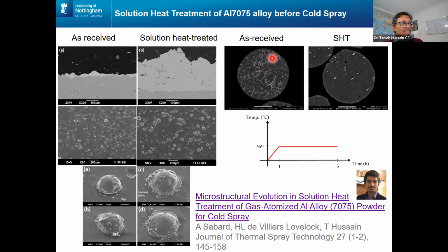And these alloys are also very difficult to spray. So these are in as received powder. You can see a very thin layer of coating, lots of rebounding, lots of particles bouncing back. And then I have got some solution heat treated powders. What we have done in solution heat treated, we have heated the powder at 450 degrees Celsius and then quenched it. And we essentially altered the microstructure of the powder. As a consequence, the particle tends to deform much better, forming these jets, more bonding, and we can see the coating under identical condition tends to be much more robust.